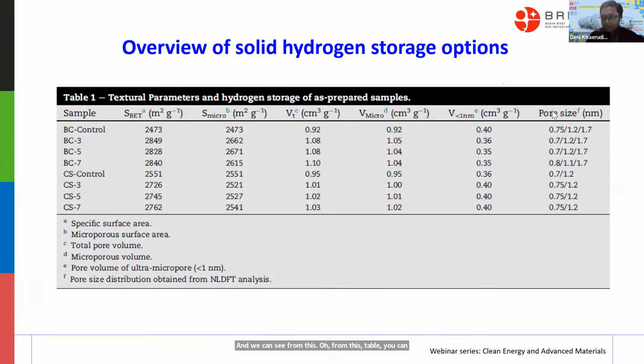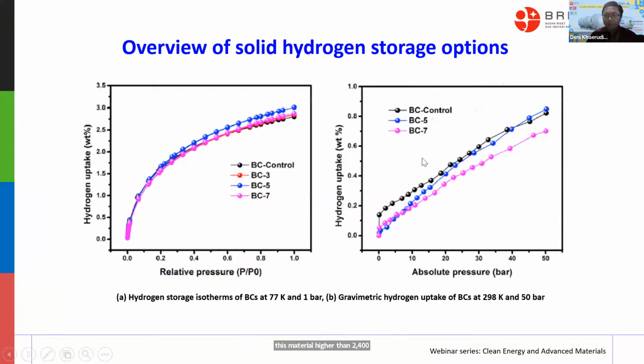this is the pore size that they achieved for all of the sample types. This is the BET surface area that they obtained. Almost all of these materials are higher than 2,400. Okay, and then about the hydrogen storage performance, like this one. On the left side is relatively low pressure, relatively vacuum, and the hydrogen uptake they can achieve is up to 3%. Meanwhile, on the right side, this is the absolute pressure. They put the pressure up to 50 bar. Previously, I showed you, there they put up to 100 or 200 bar.